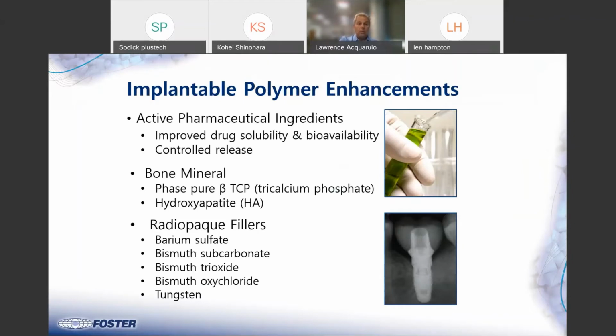Hydroxyapatite is another bone mineral material. Something else that we've used, although not a lot, it's the newer technology, is some of these resorbable glass. We've done a few experiments with that. We don't have a commercial product, but that's another additive that could go into these bioresorbable polymers. Radiopaque fillers, barium sulfate. Again, most of these polymers are transparent to X-ray. So if you want to see the polymer wherever you're implanting, you might use a barium sulfate or bismuth. I'd have to say there's not a lot of suppliers that allow those ingredients to be used. However, there are a few applications.